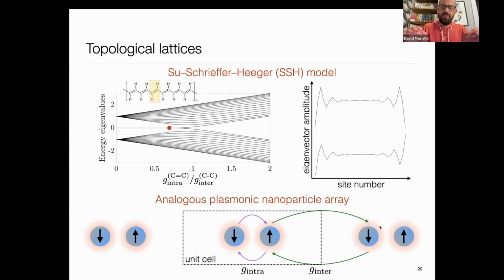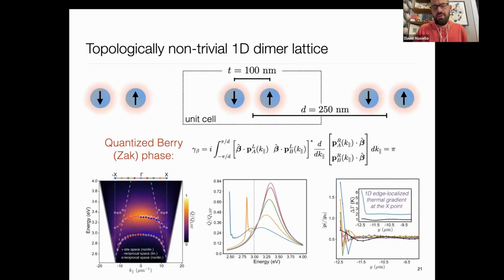So we had this idea of, can we tune the hopping rates by changing the interparticle spacing both within the unit cell and between unit cells in order to drive the system into a non-trivial topological regime. There are, I should caution, major differences between the SSH model and that of plasmon lattices. Most notably, the SSH model is a nearest neighbor model, whereas in the plasmon lattices, all dipoles across the entire lattice all communicate with each other. Nevertheless, we were able to go through and calculate the Berry phase, which was an extremely painful, tedious task to do, to verify that we had pushed our system into the non-trivial topological regime.